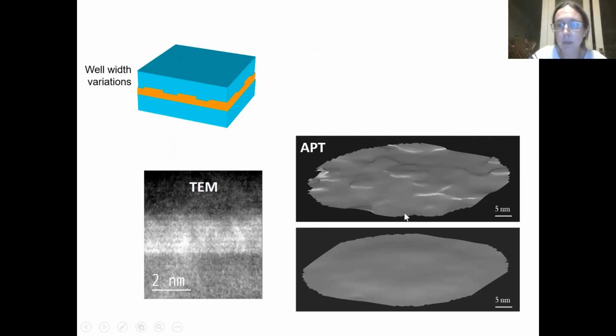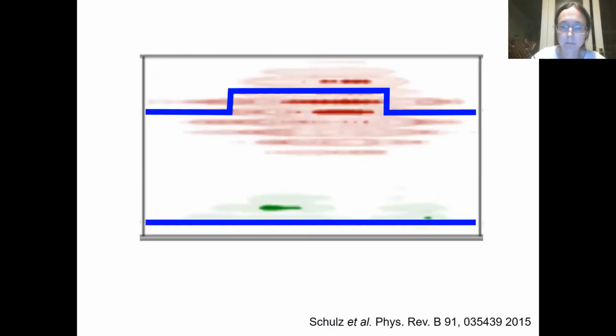In the atom probe, we can create something we call a compositional isosurface. This is a surface which links points each of the same composition. When we do that, we see again the bottom interface is very, very smooth, but the top interface has these lumps in, very much. These are a few nanometers across. These are exactly the sort of structures I'm drawing schematically here, which might confine the electron and the hole, and prevent them from moving to the defects.